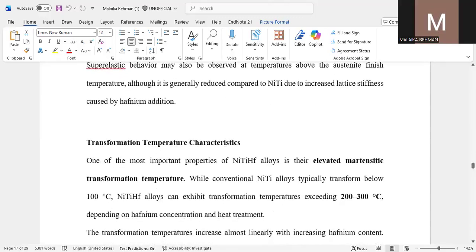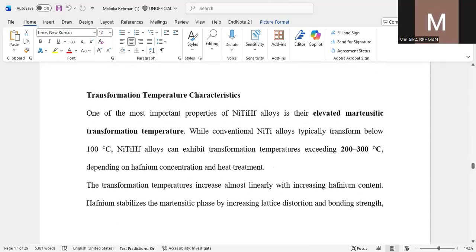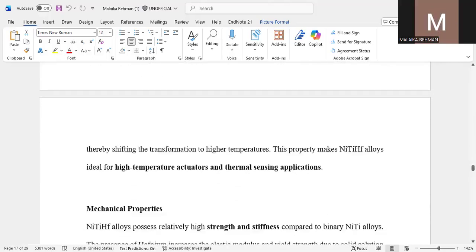It increases the stiffness of the lattice, which is a main cause of the addition of hafnium. The transformation temperature characteristic: one of the most important properties of the alloy is the elevated martensitic transformation temperature. While conventional nitinol alloys show typical transformation below 100 degrees Celsius, nickel titanium hafnium alloys can exhibit transformation temperatures exceeding 200 to 300 degrees Celsius, depending upon the concentration of the hafnium used in the material and the heat treatment. The transformation temperature increases almost linearly with increasing hafnium content. Hafnium stabilizes the structure, and it is also ideal for high temperature actuators and thermal sensing applications.